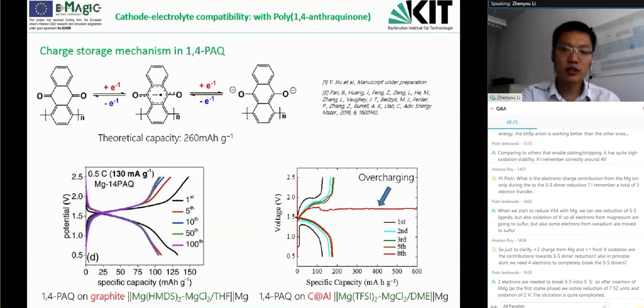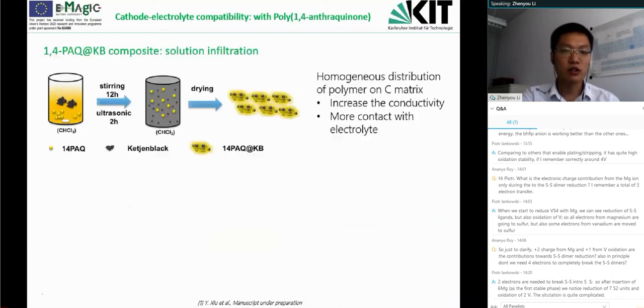As shown here, the cell could only be charged and discharged for a couple of cycles and then ends up with a very long overcharging, which indicates some corrosion happening. So the corrosion can be somehow mitigated by using a chlorine-free electrolyte system, but we also noticed that the low capacity might be from the cathode formulation.